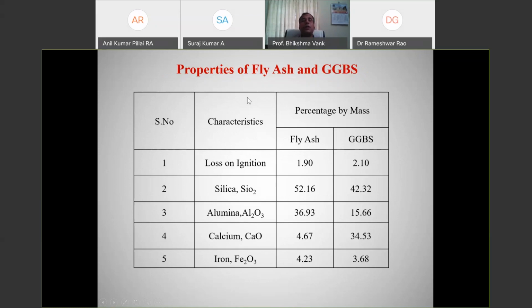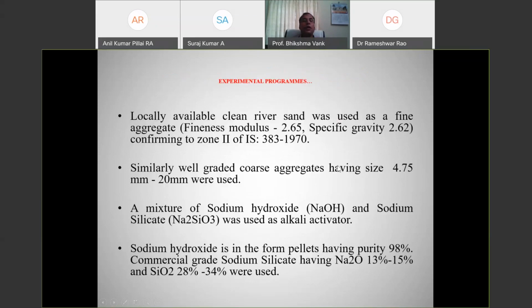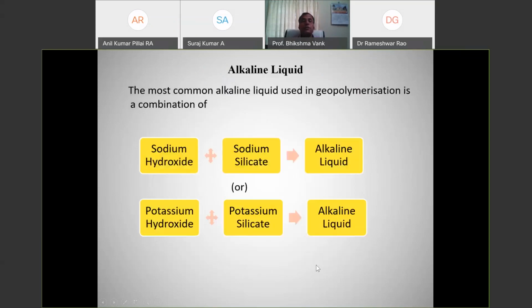We arrived at the percentages by mass and the physical properties, and these are the locally available materials: fine aggregate and coarse aggregate. The additional materials used are a mixture of sodium hydroxide and sodium silicate. You can even use potassium hydroxide and potassium silicate, but they are quite costlier compared to sodium hydroxide and sodium silicate. So that is how we have selected. To make the geopolymer concrete, this is the combination: sodium hydroxide and sodium silicate give an alkaline liquid, and potassium hydroxide and potassium silicate also give an alkaline liquid. The first combination is better and cost effective.